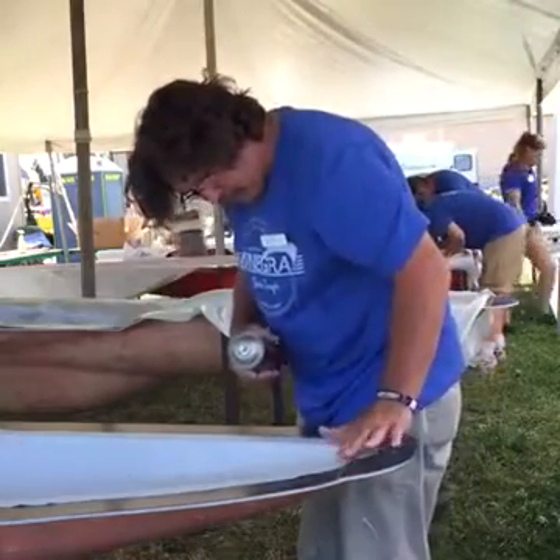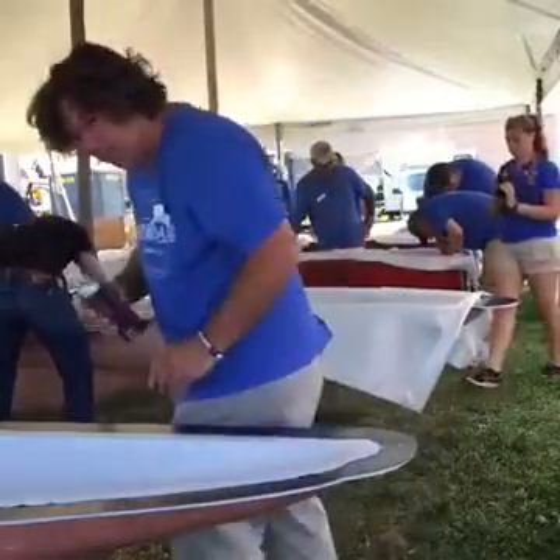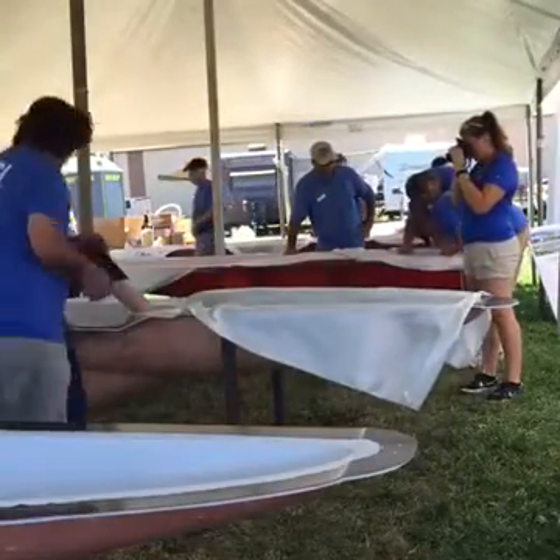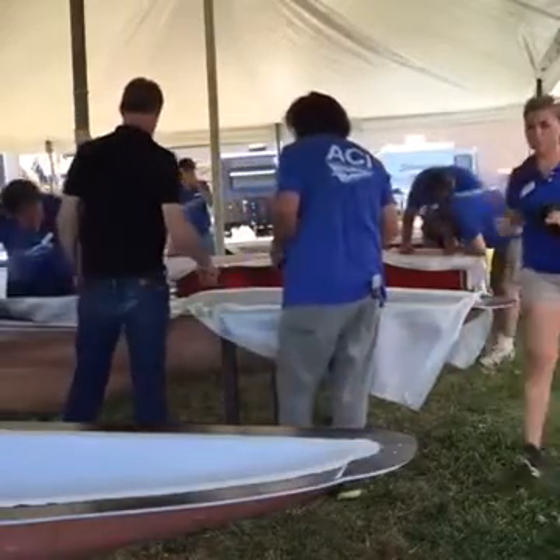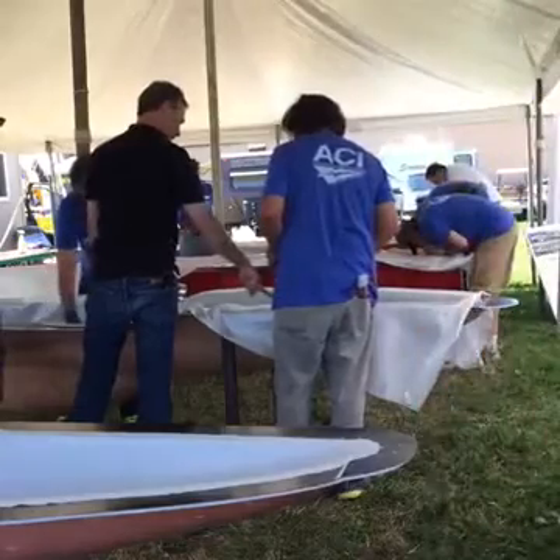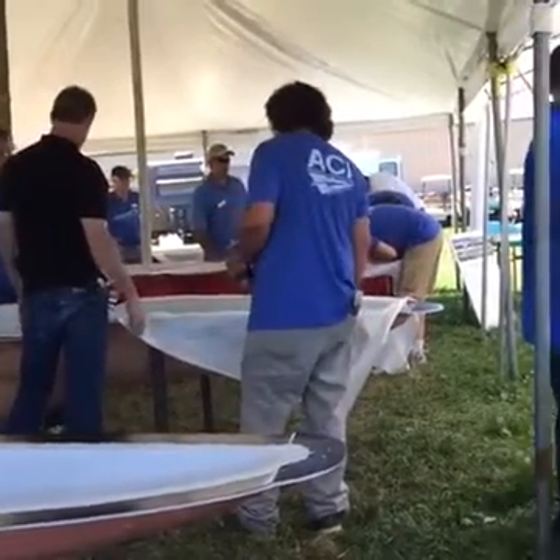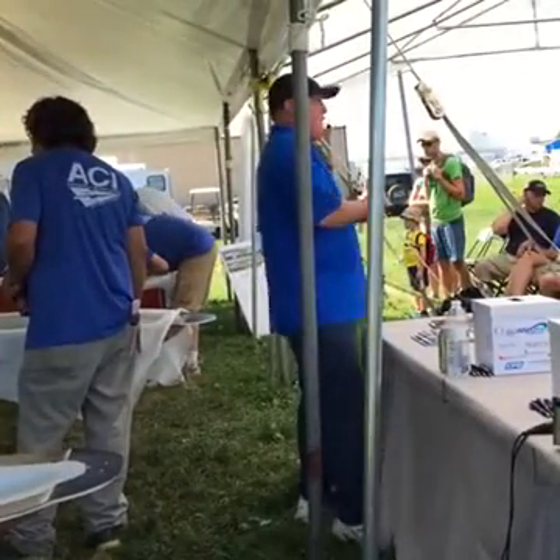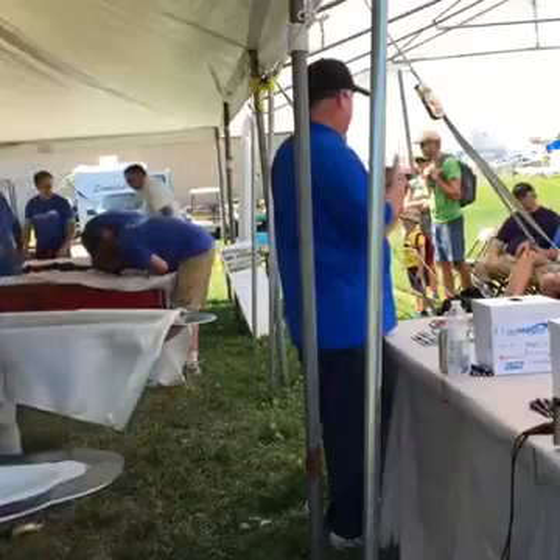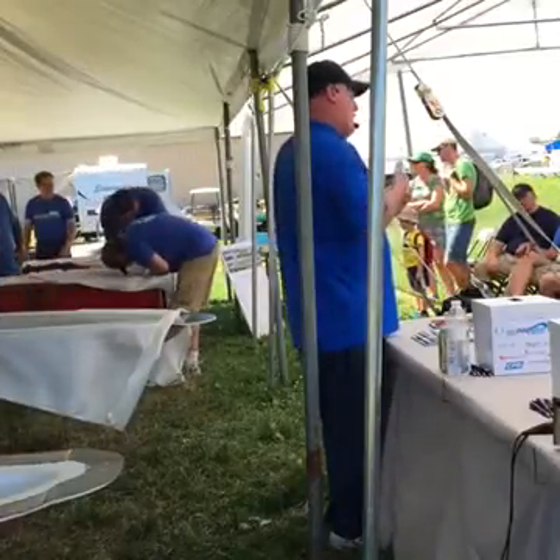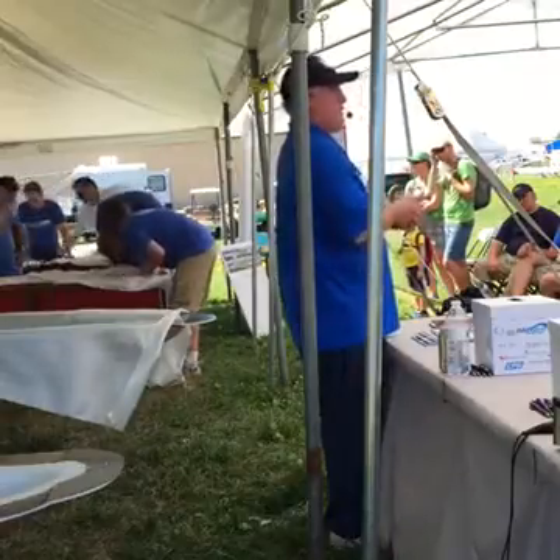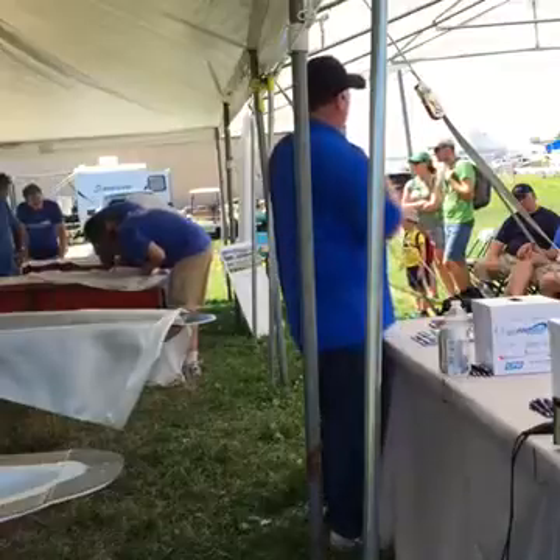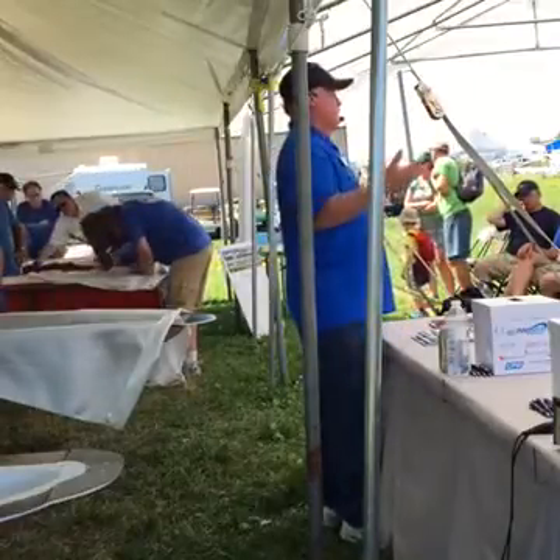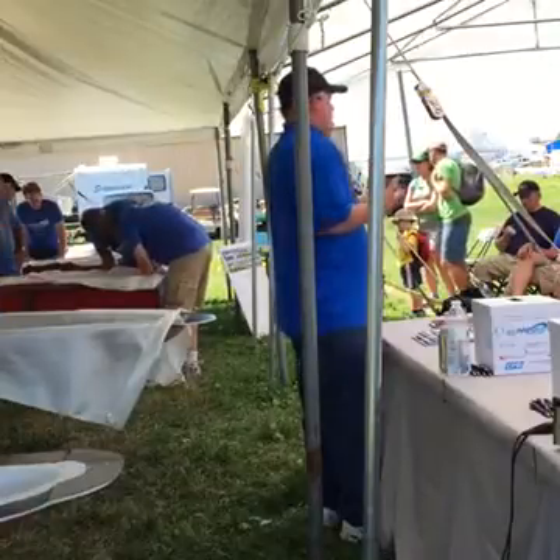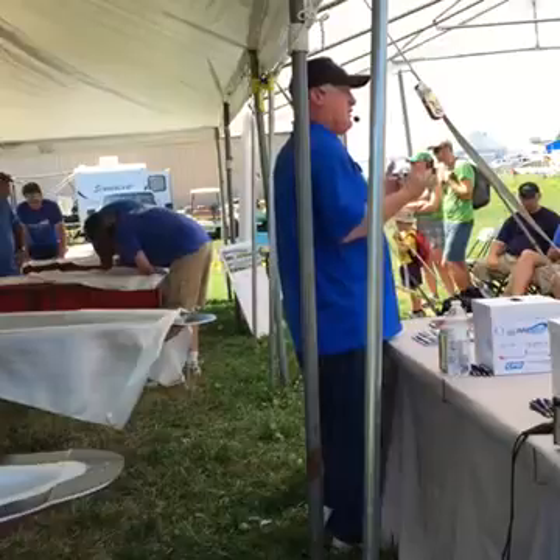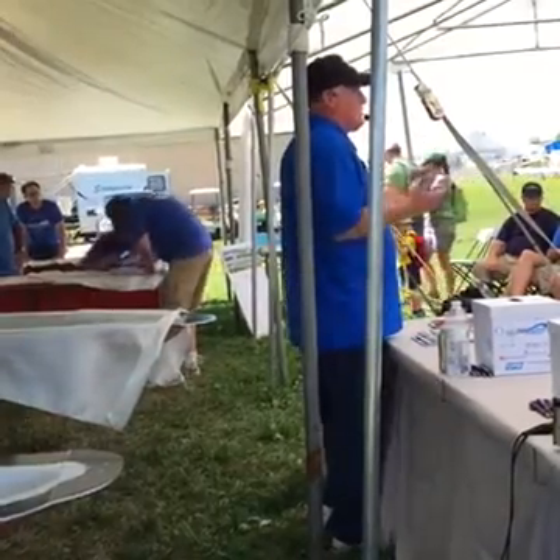Well, a lot of times when you use a tacky tape in a high temperature, low elongation bag, under pressure, the bag will actually burst. And so they decided that... loss of the part, and so it works very well. Working at Lockheed Martin and managing a lot of the composite processes on the midsection of the F-22 for Lockheed Martin, I started looking at what we were doing and how those blown bags were saved by the second bag, and I started to think about what is it I could do to utilize this in infusion, and how could it benefit me. So I started playing with it, and I really wasn't getting any benefit other than just taking twice as long to build the darn bag.